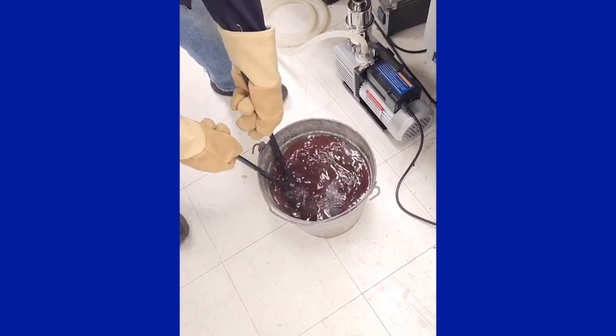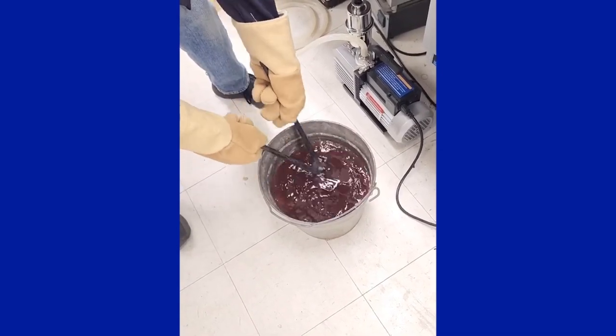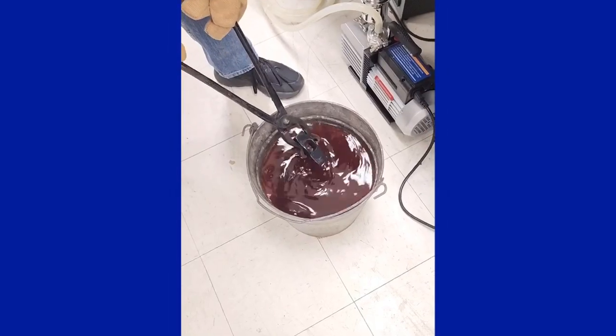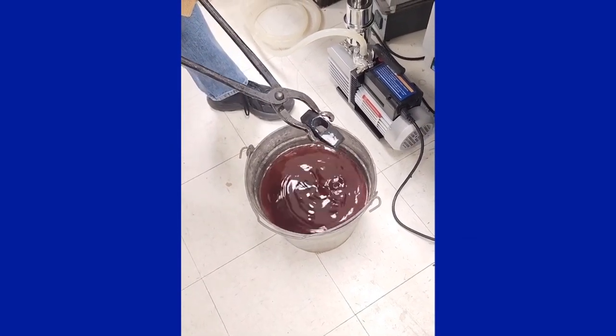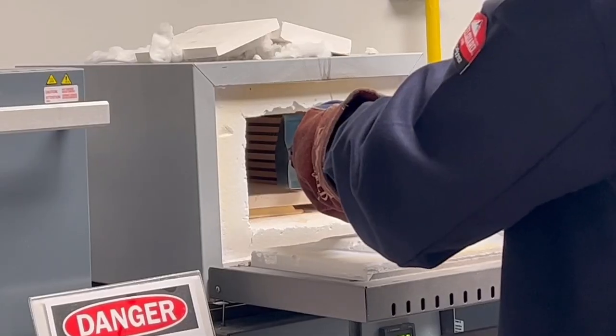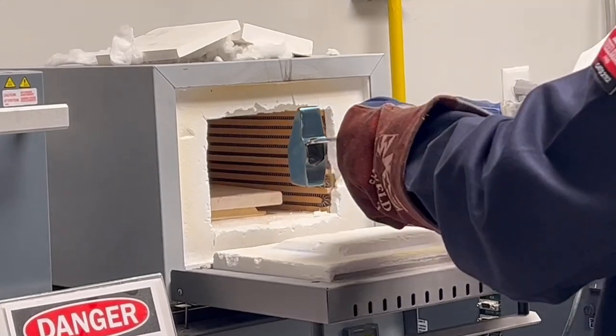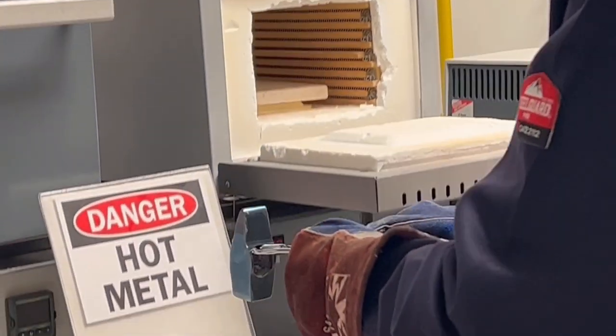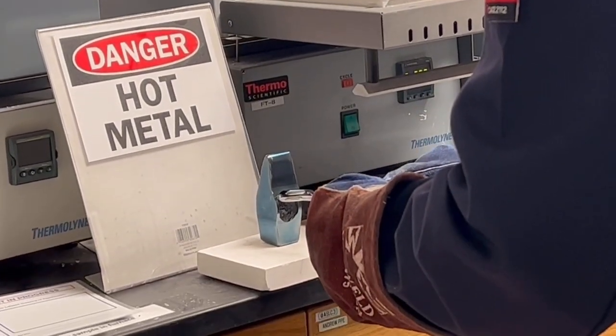The hammerhead now had a martensite microstructure. However, martensite is too hard for use in a cross-peen hammer, so we need to temper it. We tested 2 smaller pieces from our stock metal and determined that 300 degrees Celsius for 2 hours would be ideal for reducing the hardness, relieving stresses, and giving the steel a blue finish.